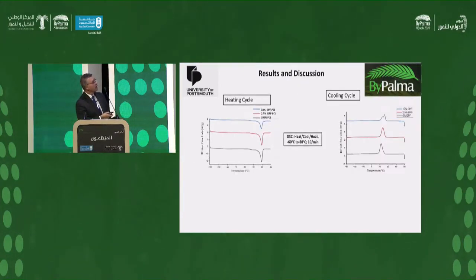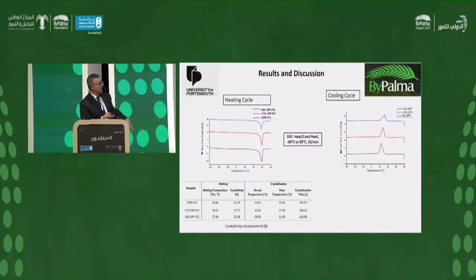So then we looked at the DSC results, the heating and cooling cycle, as you can see with different percentages of date palm fiber. The temperature has changed, and you can see here 100% PCL, melting temperature 58, and then with 2.5, 59, and 57. So it's slightly decreasing in terms of temperature, and crystallinity has also decreased because of the inclusion of date palm fiber.